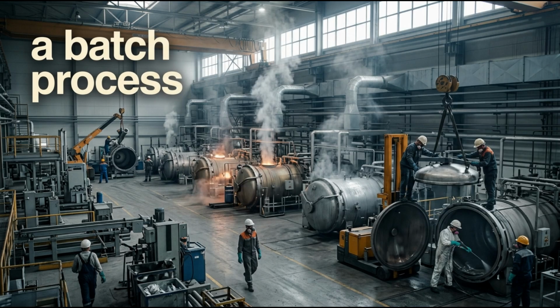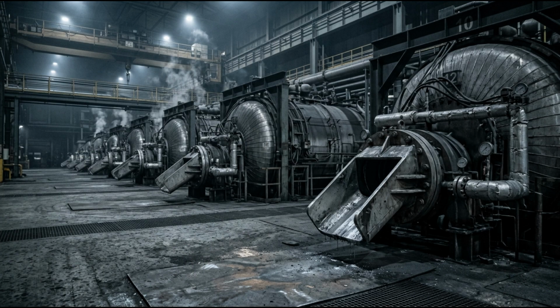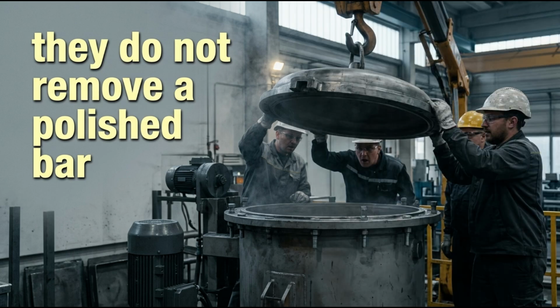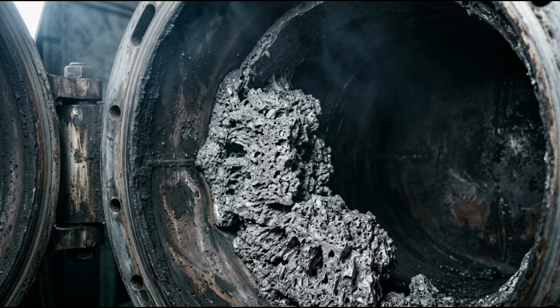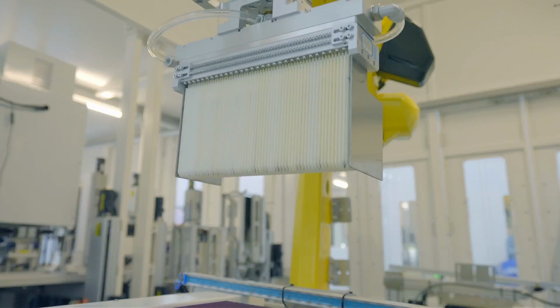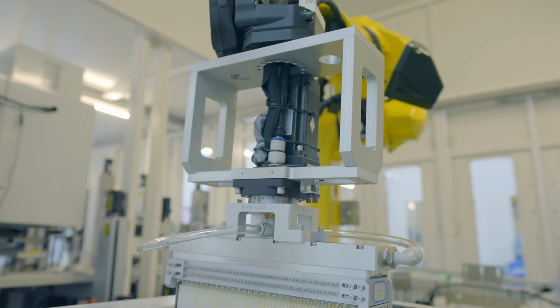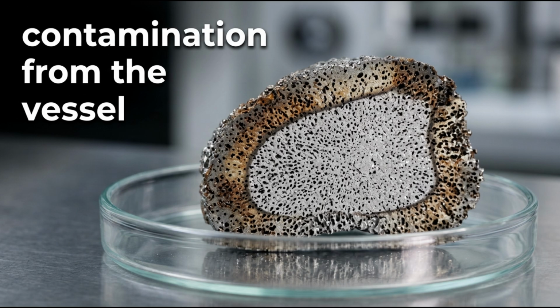The reactor is prepared, charged, heated, operated, cooled, opened, cleaned, and prepared again. Metal does not flow continuously from the other end. Each batch must complete the entire cycle. When workers finally open the vessel, they do not remove a polished bar. They find a rough titanium mass attached inside. It may need to be cut, pressed, chipped, or forced out with heavy equipment. Material close to the reactor wall may contain iron, nickel, or other contamination from the vessel, and may need to be separated from higher quality sections. This porous intermediate is titanium sponge.